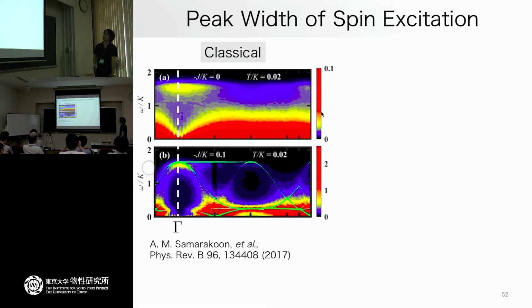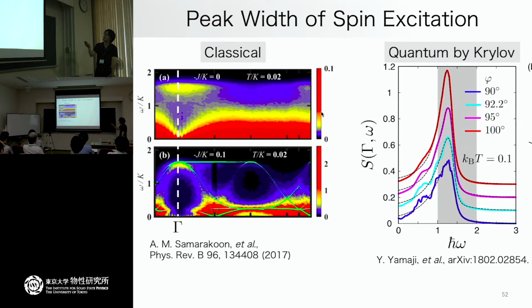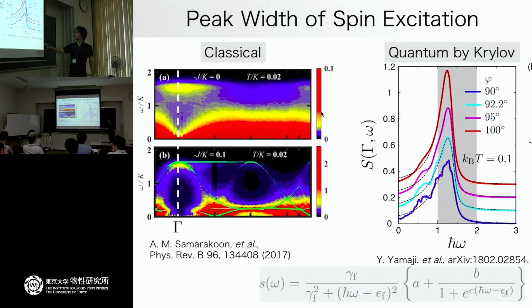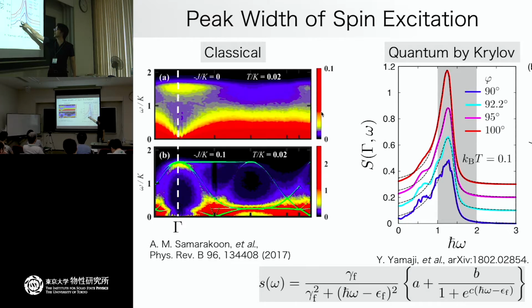Then let me compare in a more quantitative fashion. This is a classical result from the Kitaev limit and with 10% of the Heisenberg coupling. Then if we compare with this data, we pick up the spectrum at the gamma point, just cutting along this direction, and I have this kind of spectrum as a function of omega. Here the red one is at 100 degrees, and the blue one is 90 degrees, the Kitaev limit. The difference is not so visible, but if you measure the ratio between the peak energy scale and the width, then we will find a really striking difference.